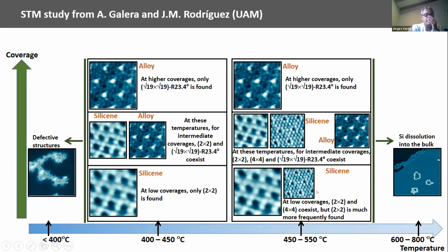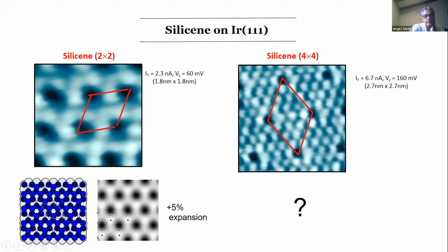Okay, so we've been fighting with these structures, first with the ordered structures, for some time now. I've done these calculations with my postdoc Araceli. We've tried a lot of structures, lots of them, and so far we have had no success. This is the closest we have got to the 2x2 structure, which would be a silicon bilayer forming 2x2 with just one missing atom. But I think we're still far from being convinced that this is the structure. And quite surprisingly, the 4x4, which seems quite simple, since there should be some silicon missing here, we're really having trouble retrieving this kind of structure.